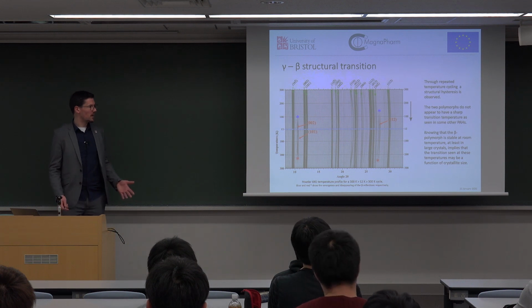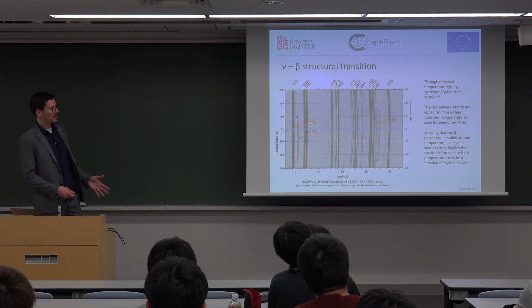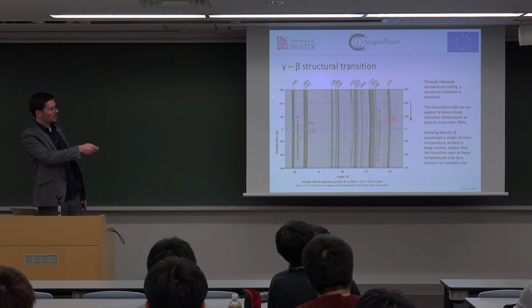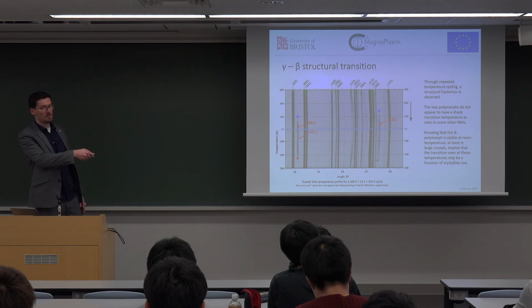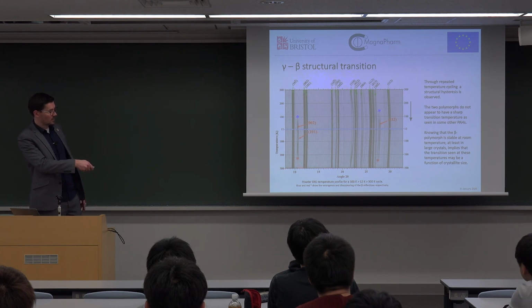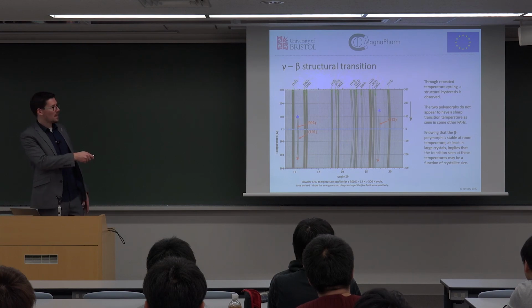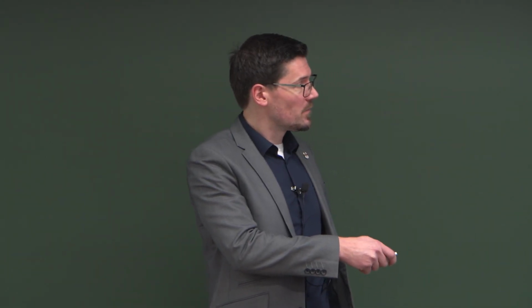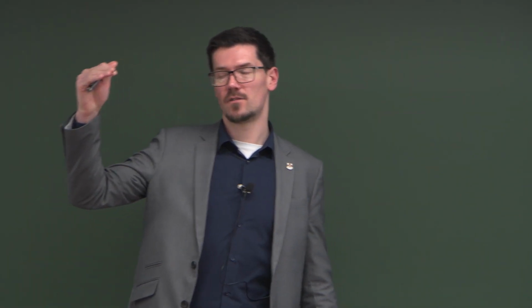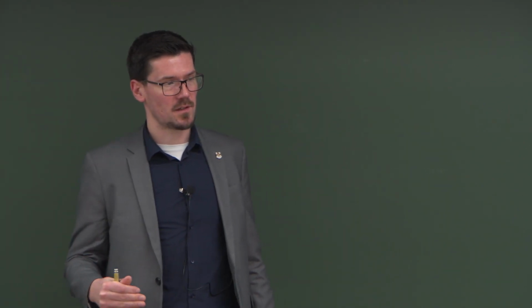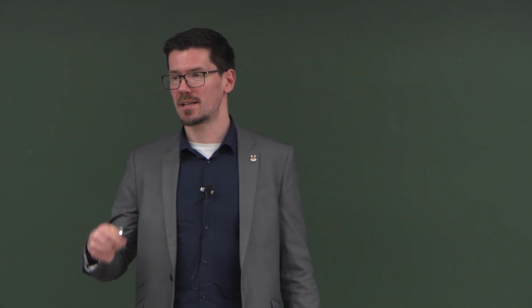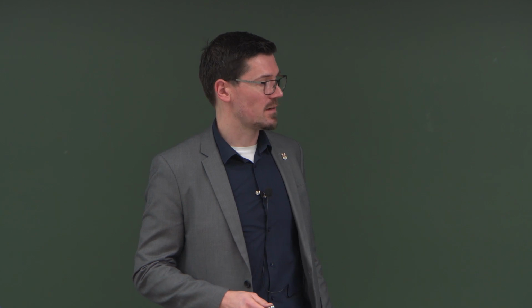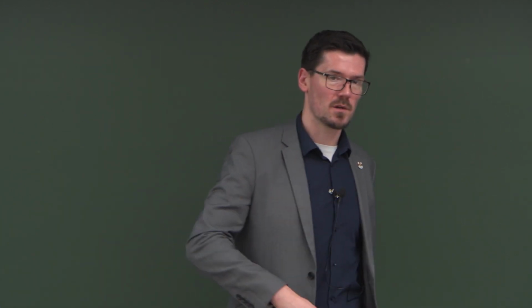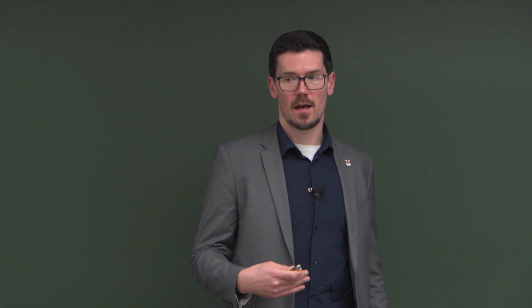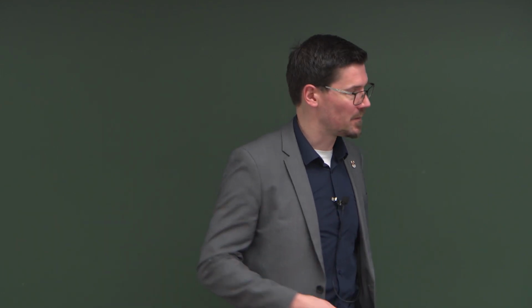This graph might look a little confusing, but effectively what we have, from left to right, is a powder diffraction pattern with angles 5 to 35. From the top to the bottom, we have temperature going from 300 to 12 Kelvin and then back up to 300. So we took a powder diffraction pattern every couple of degrees all the way down to 12 Kelvin, and then we brought it back up to 300 and took a powder diffraction pattern every couple of degrees.